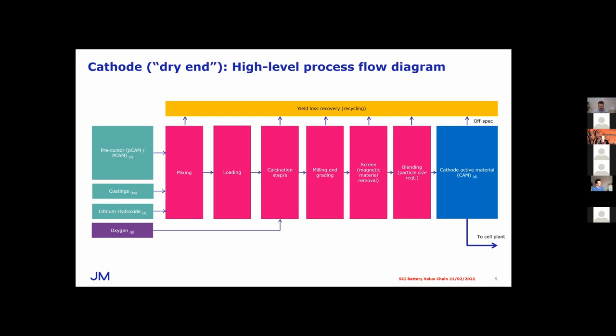The nuance around the coatings is that particularly for high nickel chemistries, where you have low cobalt and manganese content, the stability of that cathode material over the lifetime of the cell can be a bit problematic. And what the coatings generally tend to do is stabilize your crystal structure and prevent damage to it from the process of the lithium ions going in and out of the cathode material itself. And here we see a variety of novel coatings used, things like alumina or zirconia, which have shown good effects for a long time in creating higher performing cathode materials.